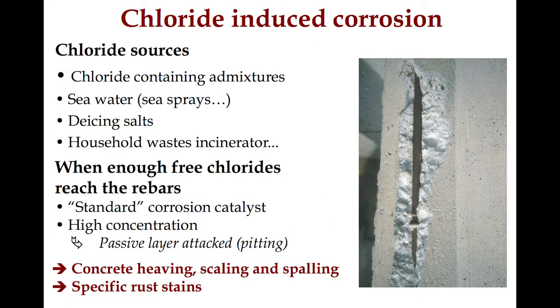Concerning the chloride-induced corrosion, there are many chloride sources: chloride-containing admixtures, seawater with sea sprays, de-icing salts, and household waste incinerator. When free chlorides reach the rebars, there is an increase of the steel corrosion. Chlorides are a catalyst for the steel corrosion. And when there is a high concentration of free chloride, the passive layer of the steel is attacked with pitting. So the main decays are concrete heaving, scaling, and spalling, and they are specific rust stains.